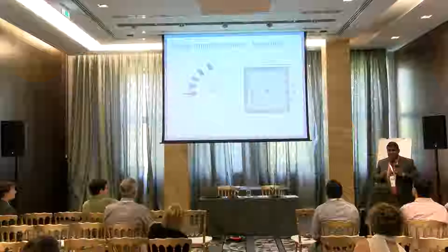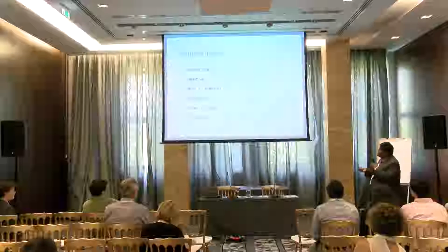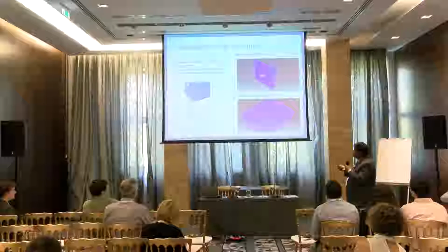We have also considered the projectile impact at different angles and at different velocities, starting from 5, 30, 45, and 60 degrees. And the fabric was fully clamped, with 1 millimeter at the four edges. That's why it shows 101. So 100 millimeters is the effective side length, and 1 millimeter is the clamped area. In this direction are the warp yarns, and the fill yarns run in the perpendicular direction. So let's first look at this 1D model.